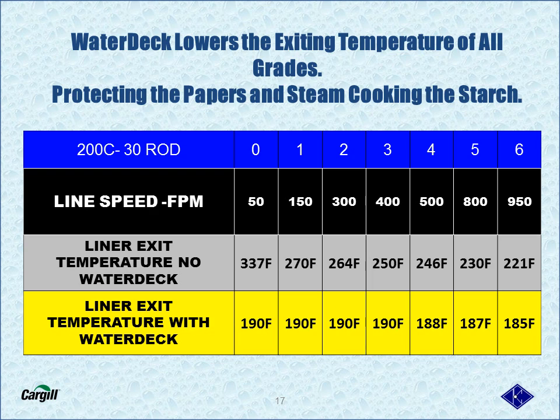At the double backer, this chart represents the speed taken with the temperature gun just as the bottom liner exits the double backer. Something that we all know is when you slow down a typical corrugator, the temperature of the board climbs significantly because you don't have the ability to shed heat as fast as the speed changes. As the line speeds up, even though you might be putting down ballast rolls on a typical double backer, temperature is going to fall off, and then eventually at the highest speeds, the board will be within a range that might be considered acceptable in a typical corrugator.